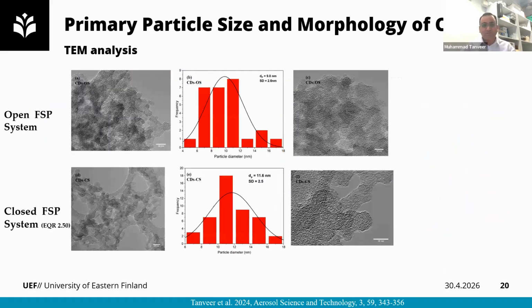Next, we established the primary particle size and morphology of the carbon dots through TEM analysis. As you can see, for the open system, because of having quite a small number of particles, and also due to rapid quenching of the flame, we experienced a small particle size, around 9.6 nanometers mean value. And due to fast quenching of the flame, particles did not show quite good morphology. They act as loose agglomerates with some defect-induced structures.